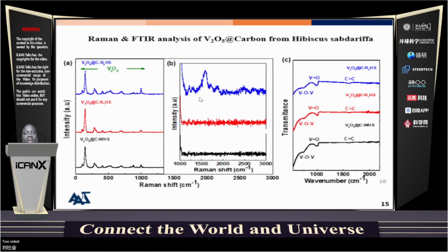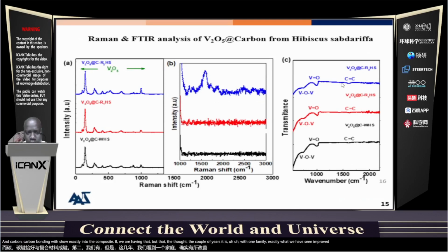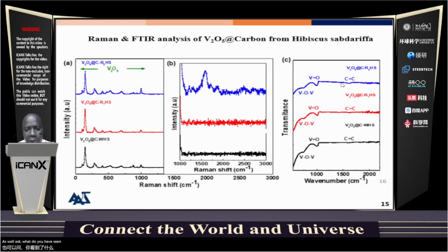To further investigate the presence of the carbon as well as the vanadium pentoxide composite, we look at the Fourier transform infrared spectroscopy of the different samples. We could see the bonding between vanadium and oxygen appearing here, which is a signature that we have vanadium oxide, and the absorption band due to carbon-carbon bonding shows that the composite contains carbon. This confirms what we have seen in the Raman, as well as in the X-ray diffraction spectrum, even if we were not able to see the carbon with the X-ray diffraction technique.